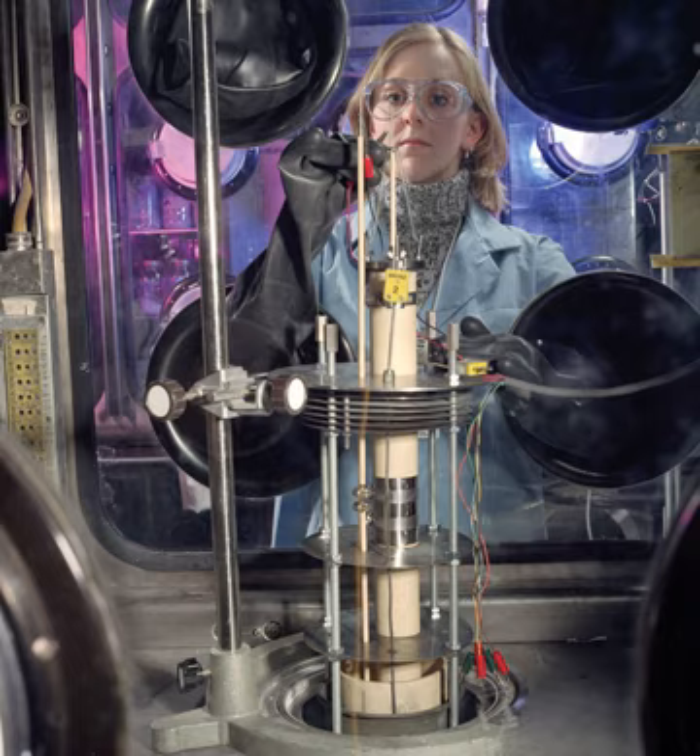The Pyro-A and Pyro-B processes were developed by Argonne National Laboratory and used in the Integral Fast Reactor Project. Pyro-A separates actinide elements within the actinide family, generally heavier than U-235, from non-actinides. The spent fuel is placed in an anode basket immersed in a molten salt electrolyte. An electric current is applied, causing the uranium metal (or oxide, depending on the spent fuel) to plate out on a solid metal cathode, while the other actinides can be absorbed into a liquid cadmium cathode. Many of the fission products such as cesium, zirconium and strontium remain in the salt. Alternatives to the molten cadmium electrode include a molten bismuth cathode or a solid aluminum cathode.